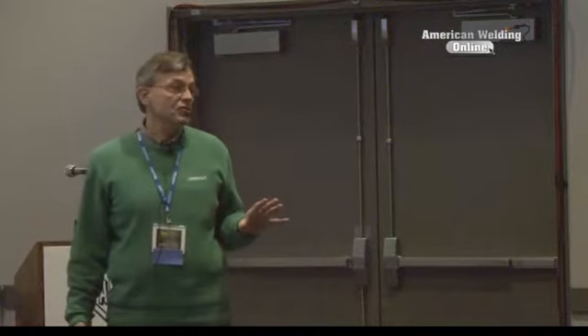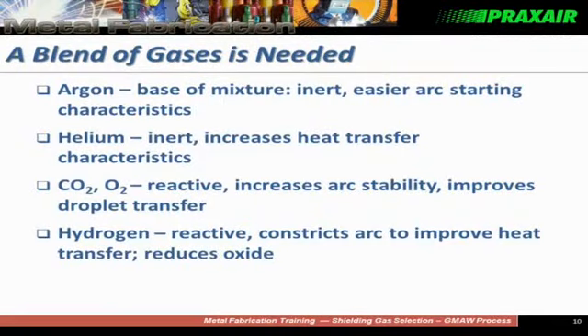So basically we use mixtures of gases because we try to balance the properties of the gases. Argon is inert, with easy arc starting characteristics. Helium has that increased heat transferability, also inert. We use materials like CO2, or carbon dioxide, and oxygen to increase the stability of the welding operation, often to increase the fluidity of the weld pool in carbon steel welding and in other materials. And then where we can use hydrogen as well. One of the interesting things about hydrogen is not only does it have good heat transfer characteristics, but it can remove oxides. It's a reducing gas, so it reacts with oxides on the surface to get a cleaner weld with less oxide, again, which could relate to less post-weld processing.